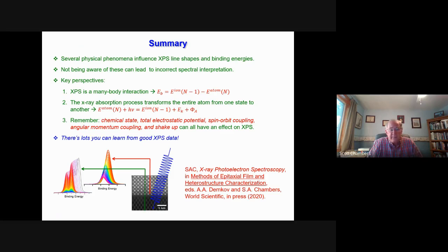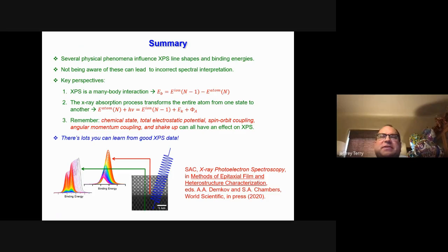And there are a lot of other papers out as well by now where people have done that for other kinds of materials. But that's if you have a superlattice, and you have to make your superlattice with certain dimensions in order to be able to tune it to the standing wave for the X-ray field. And conveniently for HAXPES, given the geometry of most systems, the standing wave is easy to set up in back reflection geometry, where the conditions are greatly reduced compared to other angles. So it is advantageous for doing that, especially with HAXPES. Yes.